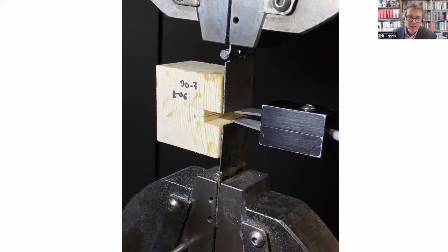Now this is going to be a specimen with an alpha angle close to 90 degrees, because the crack plane is the radial direction, but the alpha is pointed in the tangential direction. And here's a clip gauge to monitor crack mouth opening displacement. And as I said, for most of the tests, not all of the tests, we use the feedback, the output from the CMOD gauge to control the test under a closed loop system.